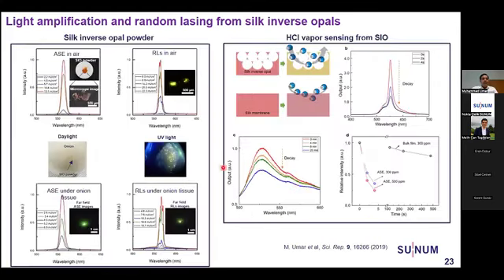And then for the application, first we made the silk inverse opal film. We crushed it into powder form, and then we see again the same phenomena of amplified spontaneous emission and random lasing in air. You can see the lasing picture. And then we utilize this powder and put it inside onion tissue. So we find that this is a good biological application. Under the onion tissue, we put this powder, and here you can see the spectra under UV light. You can see the emission color because of the sodium fluorescein. Under the onion tissue, it again had amplified spontaneous emission, and it also showed random lasing. So this means that this kind of random laser platform can be utilized to engineer or scan biological tissues.